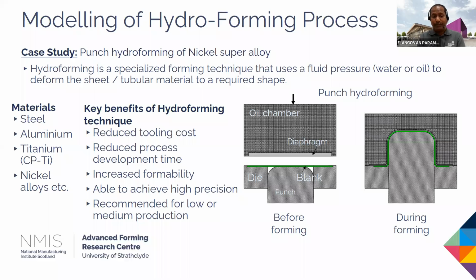The most important benefit we could see from the hydroforming process would be increased formability of the material. Unlike in the deep drawing process, where we have two different tooling elements like punch and die, in the hydroforming process we have just one tooling element. Because of this, the friction between the tooling and the sheet material is very, very low, so we are able to enhance the formability of the material. And with the process setup, we could achieve high precision of the component. It's mainly recommended for low and medium volume production.